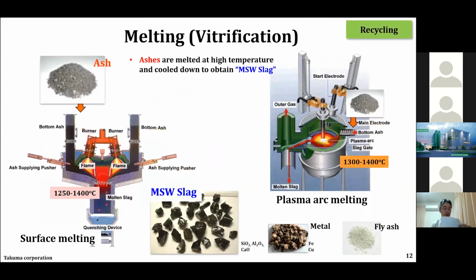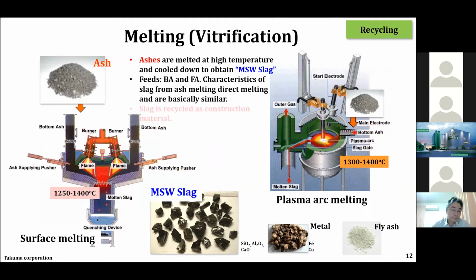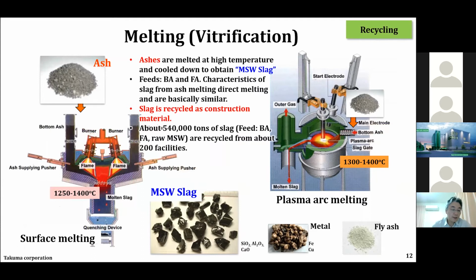In the melting technologies, ash is melted at high temperature and cooled down to obtain MSW slag. The main feed of melting treatment is bottom ash, but fly ash can also be accepted. Besides, there is direct melting of MSW, which is also called gasification melting. And the characteristics of the slag from bottom ash, from fly ash, and from direct melting are basically similar. The obtained slag is recycled as construction material, such as concrete aggregate and road construction material.